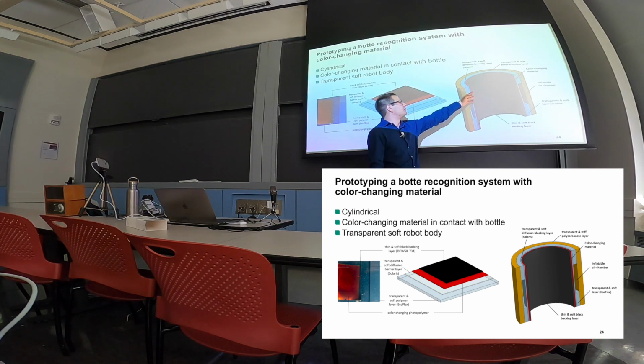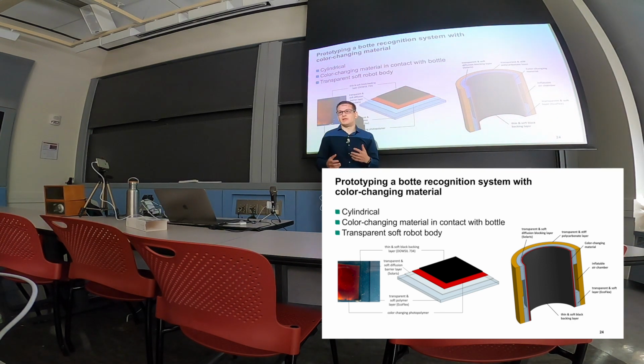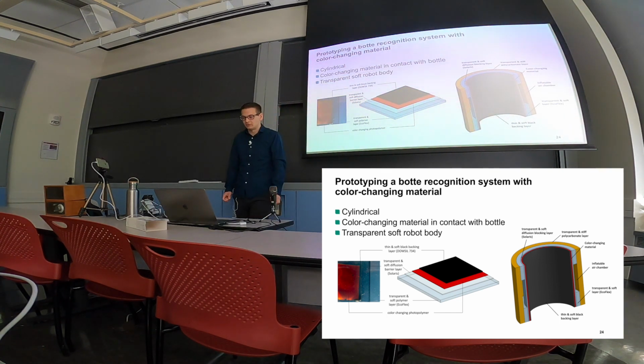And so I ended up with the black backing layer and the color changing material on the inner side, and the diffusion blocking layer, and then the soft robotic material with the chamber here to be inflatable and press against the bottle, and then the outer system is just a rigid tube, which is also transparent, so polycarbonate or acrylic, for example.